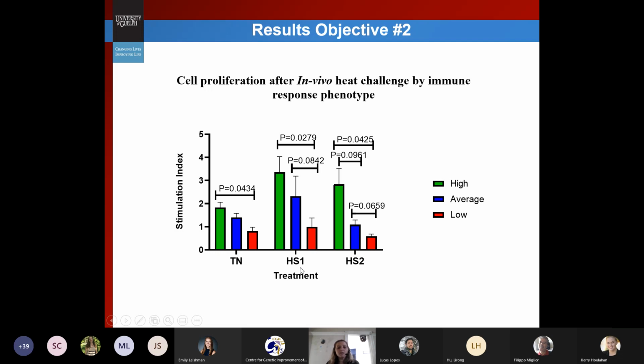So again, we're seeing after our 2 heat stress treatments, after the first heat stress treatment, we see a significant increase in cell proliferation compared to our lows. And then additionally, after the second heat stress treatment, we see a trend towards greater cell proliferation compared to averages, and again, a significant increase in cell proliferation compared to the lows.